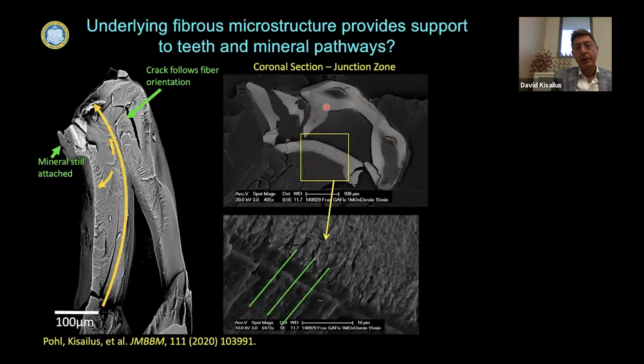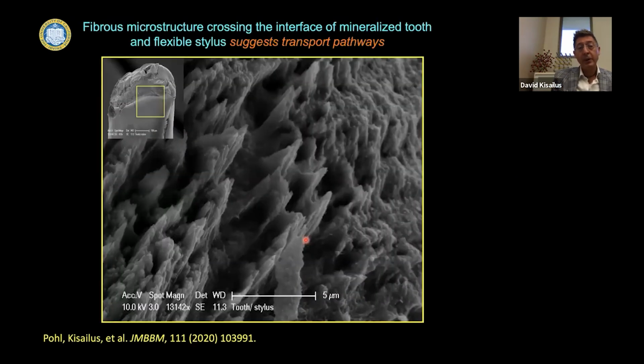So this structure is made of alpha chitin fibers, unidirectional inside the core of the stylus. The tooth would have been here. We broke it off. And what we see is that these alpha chitin fibers continue from the stylus up into the tooth. They cross the interface, what we call the junction zone, into the tooth, and they actually support the interface between the stylus and the tooth. But they also, we believe, act as conduits for mineral transport. And we can actually see a broken off tooth here at that interface where these fibers are jutting up through the stylus into the tooth.